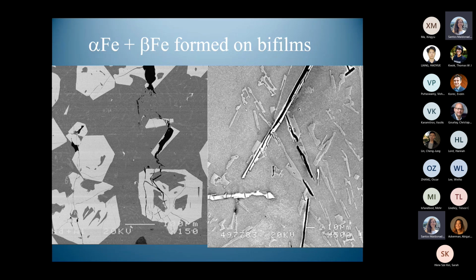And now you have a completely different situation. You have a much better property because you freeze in your bifilms in a convoluted manner. And you can see how they're all wrapped up inside here. Even so, some of the bifilms escaped into other particles, but basically most of it is ravelled up and unable to escape. Unfortunately, as I say, not all of it gets ravelled up, and some of it still remains to bring the properties down. So the bifilms are still a damn nuisance, frankly, because they do affect properties, even though you do your best to wrap them up with the metallurgy.